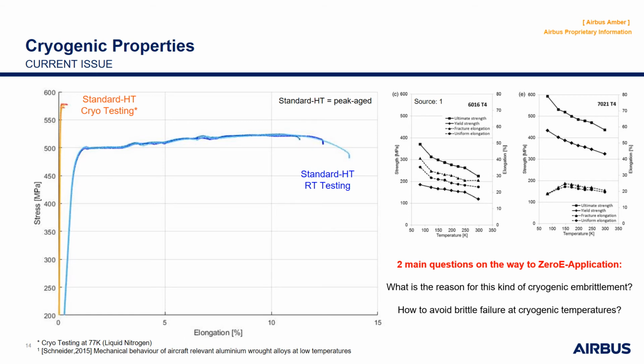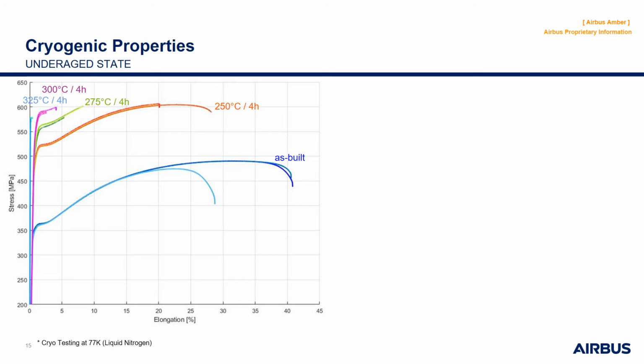So, bad news first. We still do not know what's the underlying cause for the brittle fracture in the peak aged state, and it's fairly difficult to investigate. But we already found a solution how to avoid the embrittlement, namely by an underaged state.